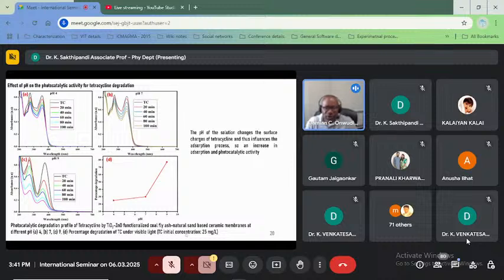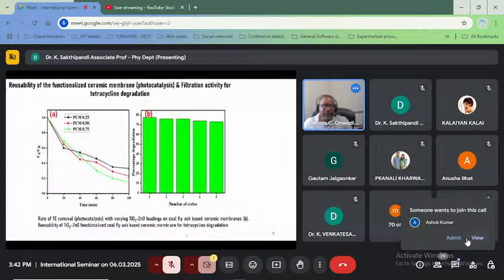So what we also did now was, because we know in the environment, the pH is not static. pH is not constant in the environment. So we need to test the effect of pH on the efficiency of this material. The process again was carried out following the same procedure or protocol. We took aliquots, we changed the pH to 4, to 7, and to 9 using sodium hydroxide, and then checked the degradation pattern. Again, we found that as the pH increases, the degradation also increased.